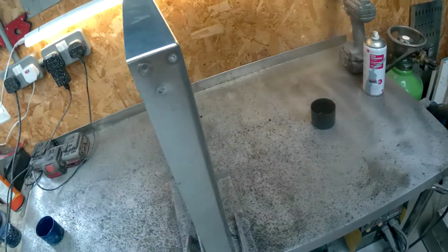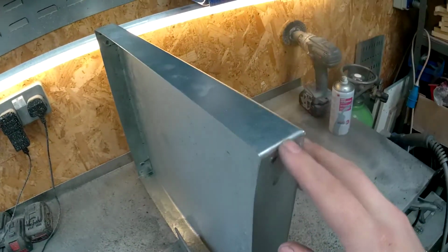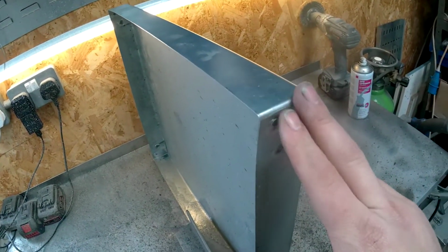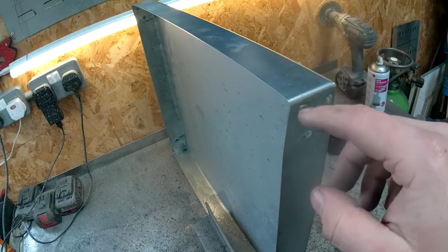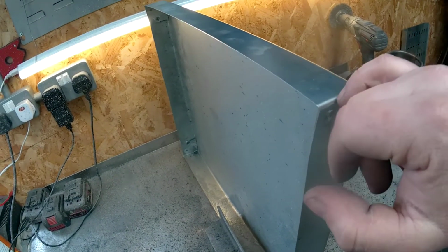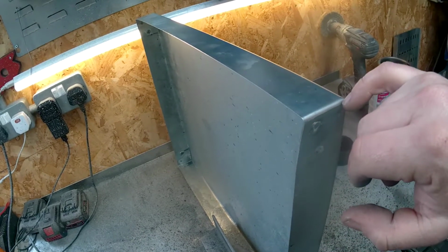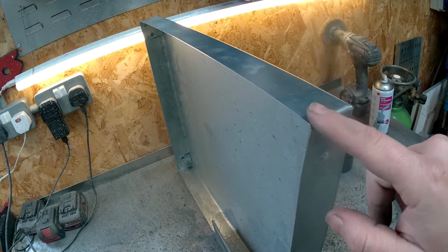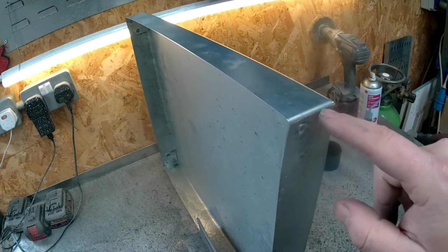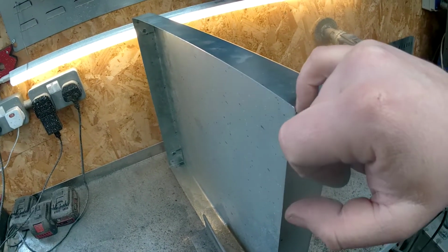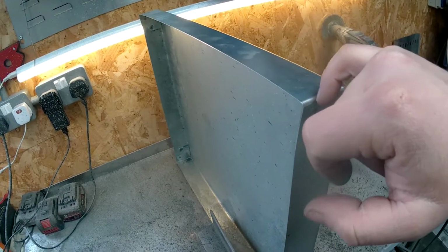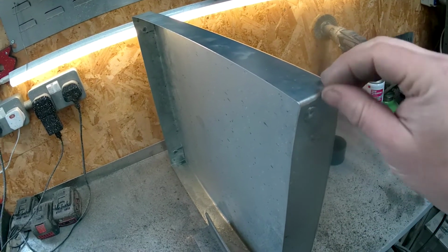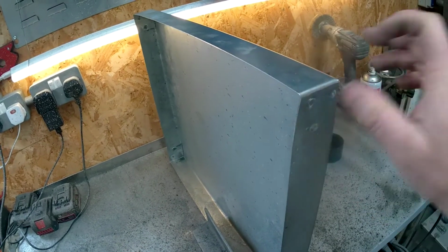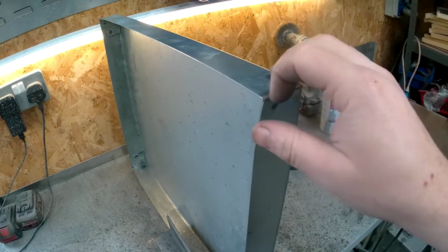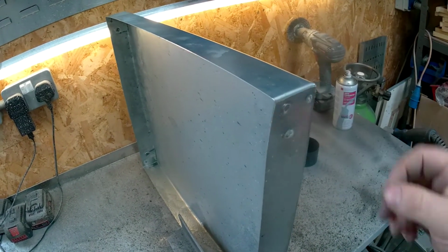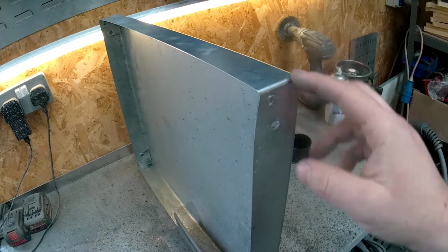So the higher the flow rate, the cooler the weld will be, and that's done by the argon, which keeps it cool. The CO2 reacts with the steel as it's melted, and helps bind both bits of steel together. Else you can get particulates in between, which actually stop them binding. And what you find, especially if you try doing this without the gas, is that sometimes you can just crack the weld apart. It may look beefy, but it'll crack.